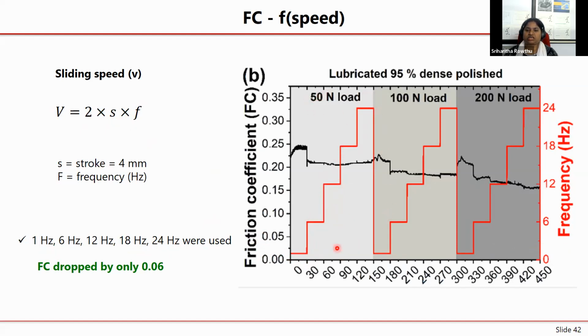Again, not just keeping load constant, but I have also changed the load. So again, you can see that the friction coefficient is decreasing, but not too much. It only dropped by around 0.06 or so. So speed and viscosity do have an influence, but it's a very small influence for this system.